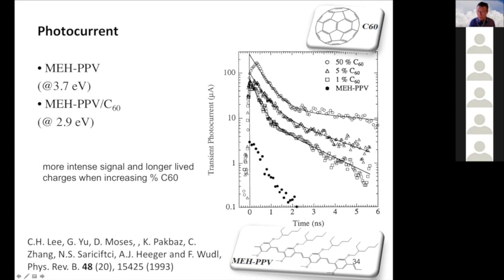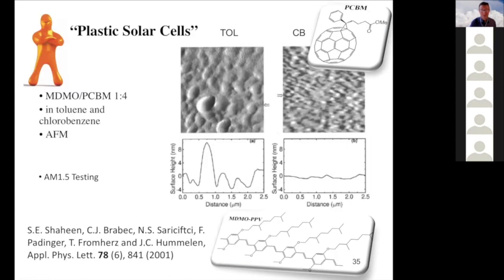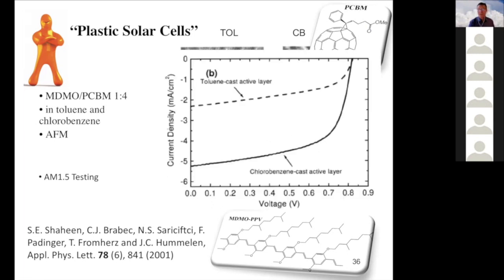We also see that when we try to measure the photocurrent generated by the polymer by itself, you see some signal, but it's very weak. By using a different solvent, you can also influence the nanostructure, and so you can influence the efficiency. Here they compare toluene with chlorobenzene, and you see in this electron microscopy picture that there's a big influence on the size of the aggregates. In toluene, the aggregates are much bigger, a couple of 100 nanometers. In chlorobenzene, the aggregates are much smaller. These smaller domains give a higher efficiency.